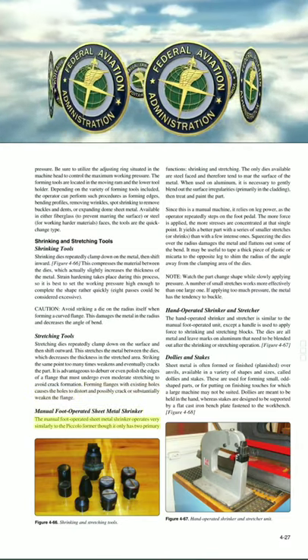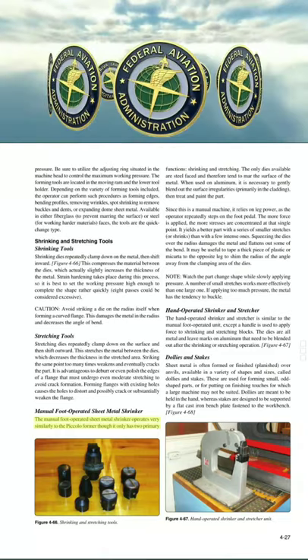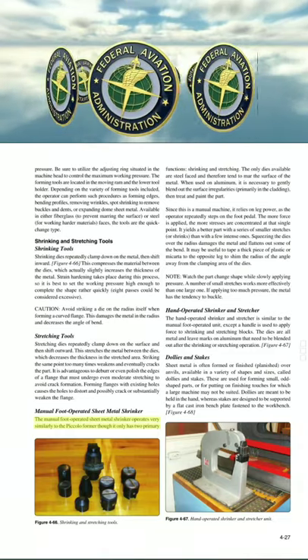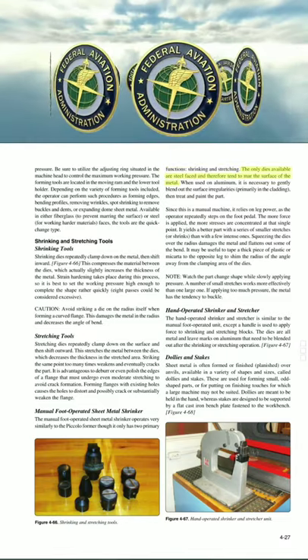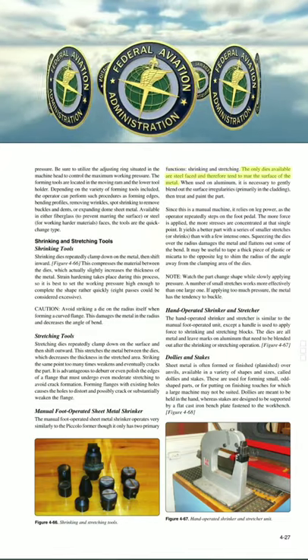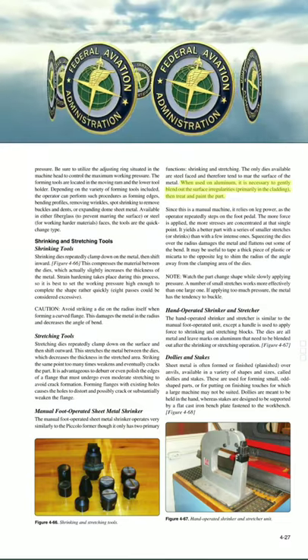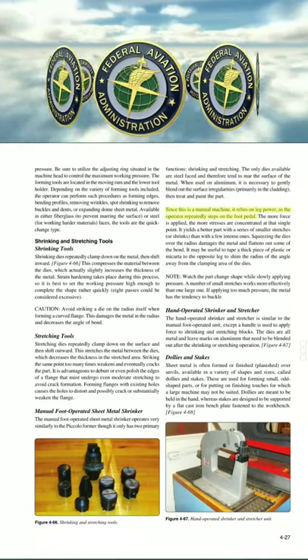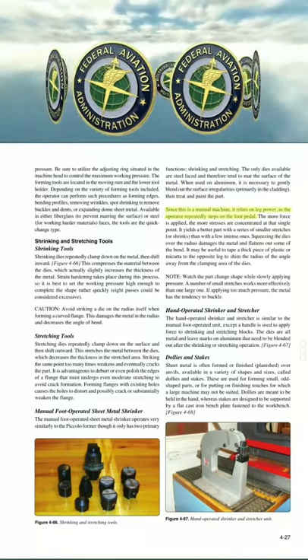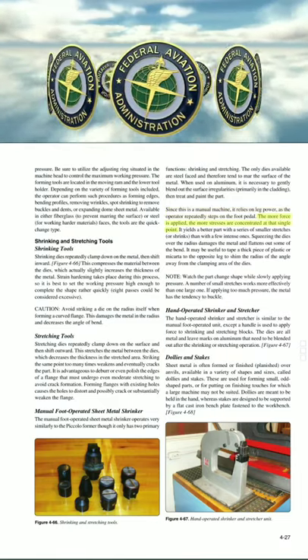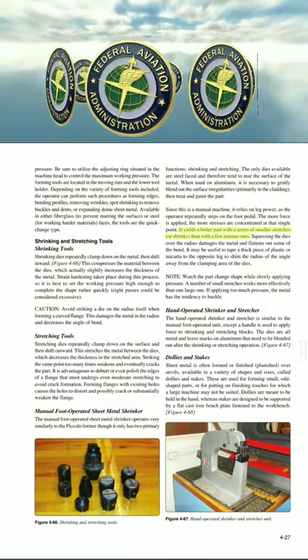The manual foot-operated sheet metal shrinker operates very similarly to the piccolo former, though it only has two primary functions: shrinking and stretching. The only dies available are steel-faced, and therefore tend to mar the surface of the metal. When used on aluminum, it is necessary to gently blend out the surface irregularities, primarily in the cladding, then treat and paint the part. Since this is a manual machine, it relies on leg power, as the operator repeatedly steps on the foot pedal. The more force applied, the more stress is concentrated at that single point. It yields a better part with a series of smaller stretches, or shrinks, than with a few intense ones.